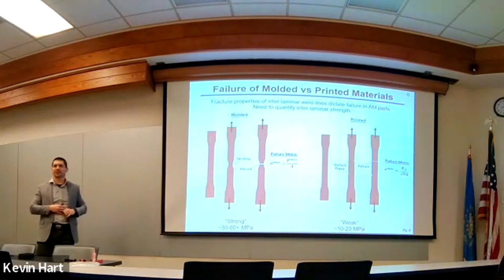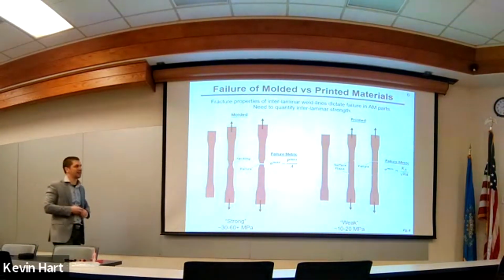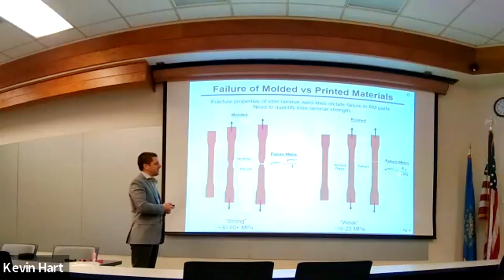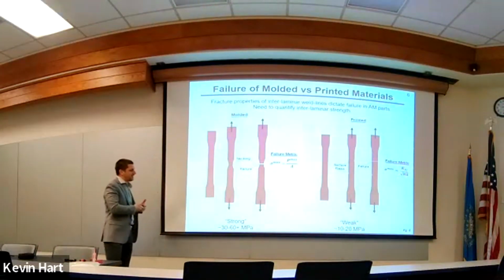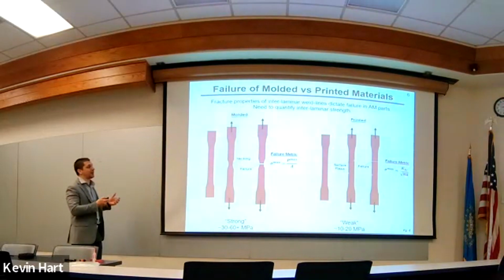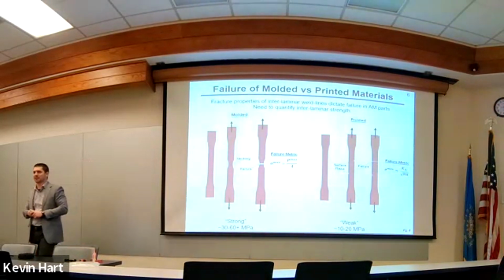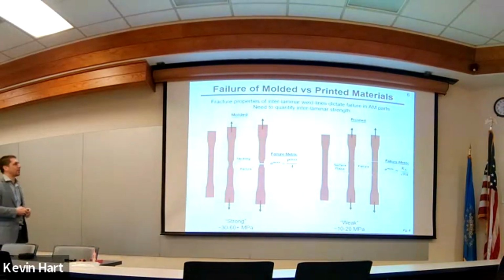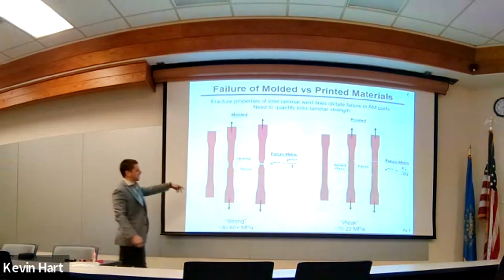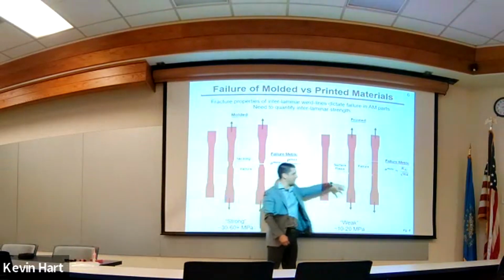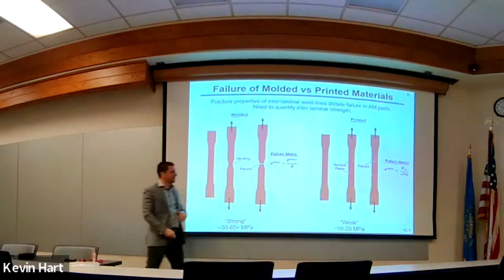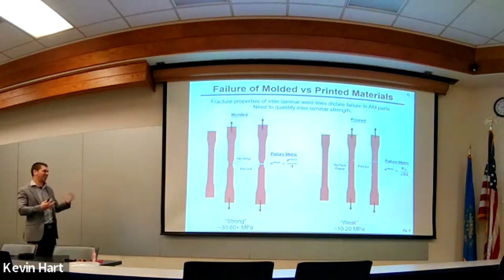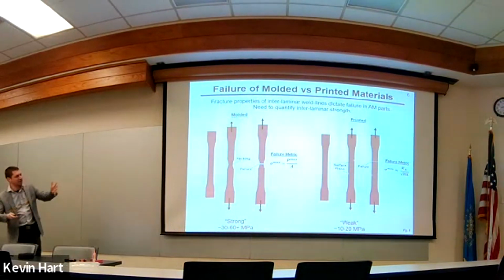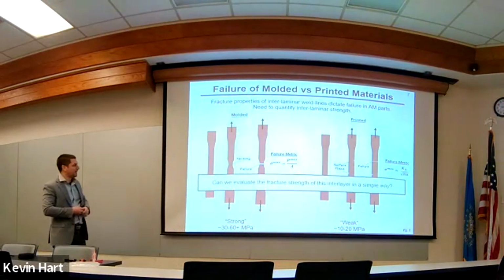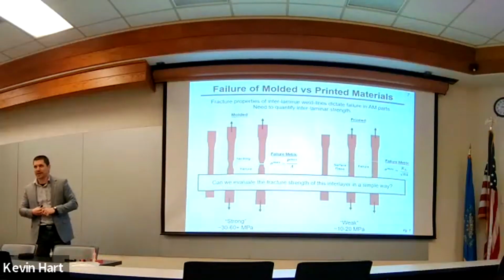And so maybe there are some people who are studying fracture mechanics. I think we have some younger people here that may not have seen ideas of fracture mechanics, but the basic idea is that it changes how you want to analyze this failure from your traditional load divided by cross-sectional area to fracture mechanics that rely on a metric called the stress intensity factor or critical strain energy release rate, depending on what metric you're using. So you might see this as strong if it's injection molded, and you might see a 3D printed sample as weak when you're testing in tension. But it didn't really make sense to me personally to look at tension testing because you're really investigating fracture, not tension.